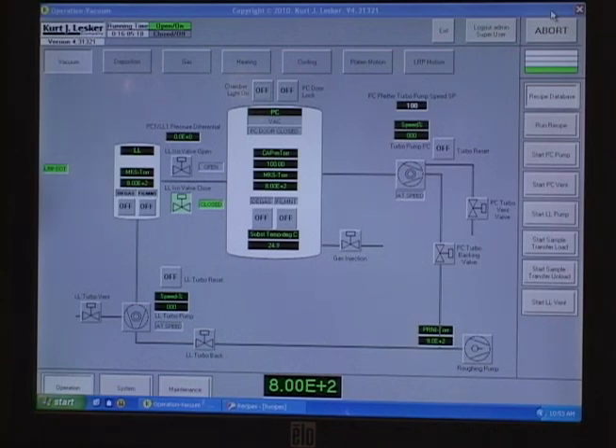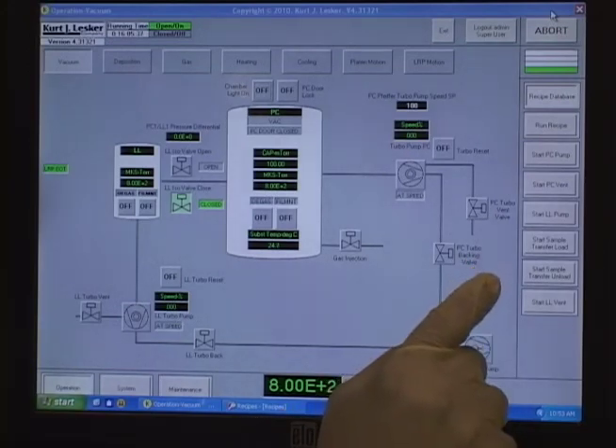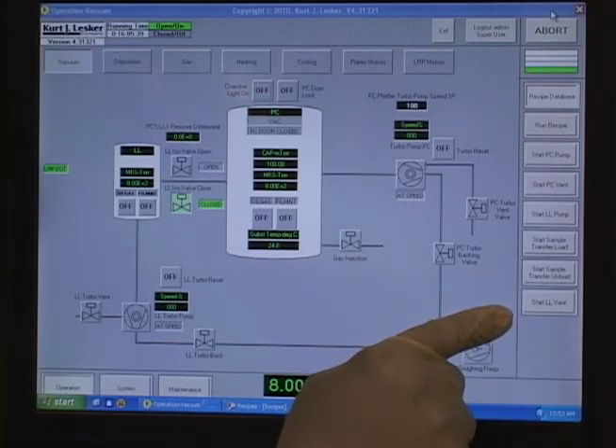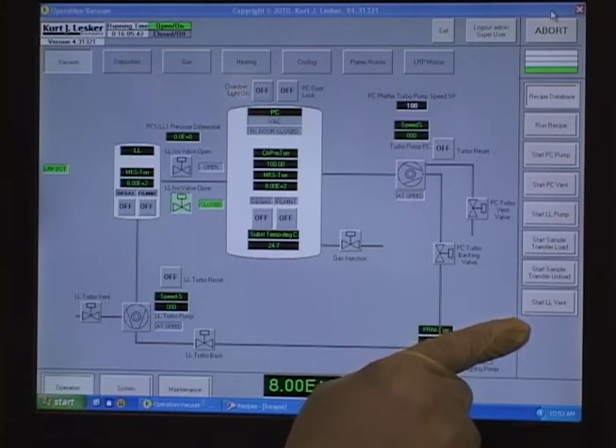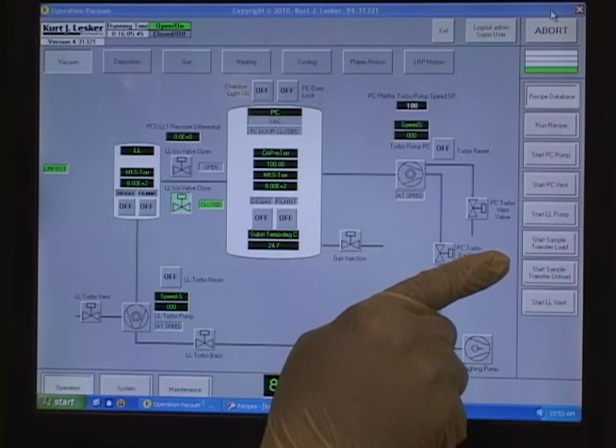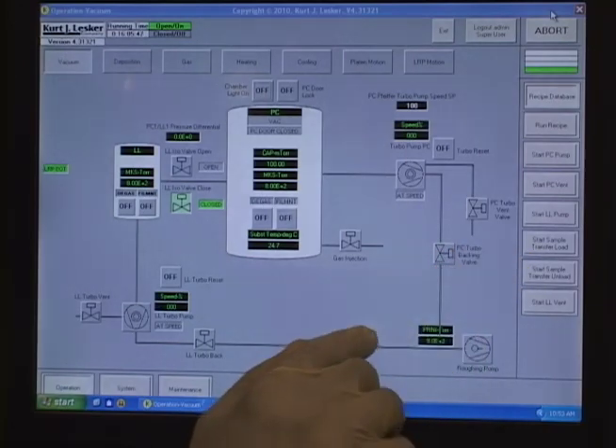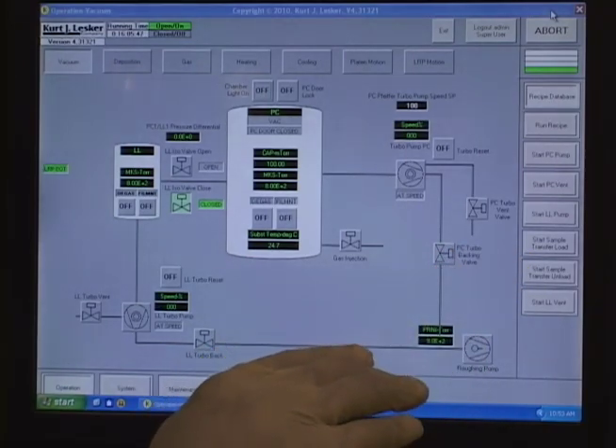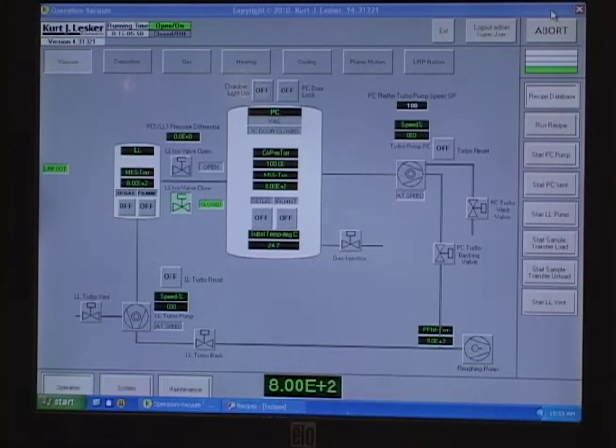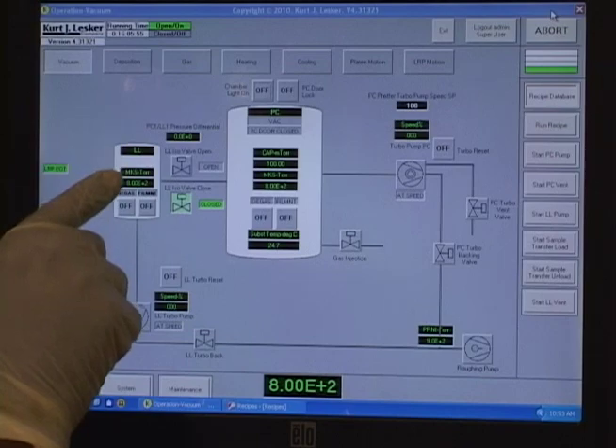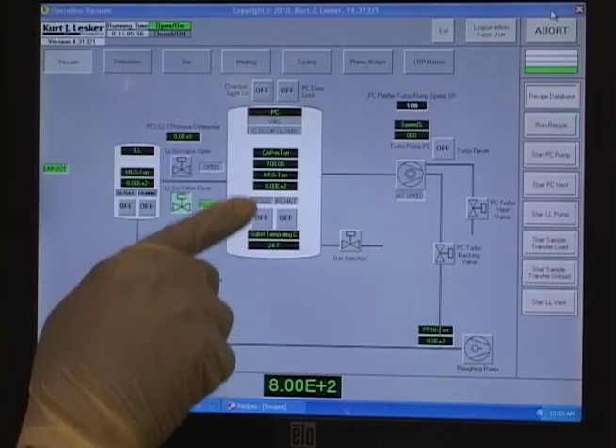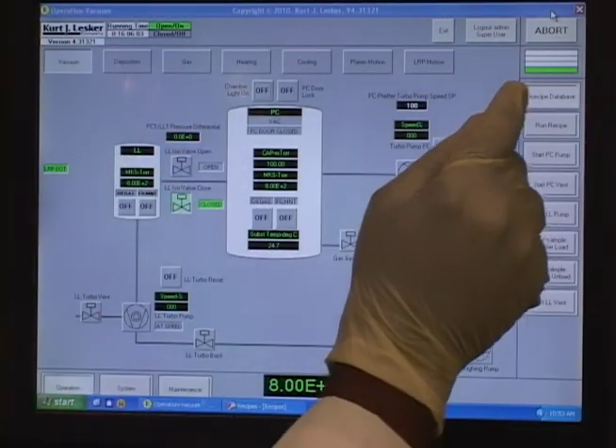Then the next step is to transfer that sample into the deposition chamber. And we do that by the third button from the bottom, which says Start Sample Transfer Load. So there's a mechanical arm that would actually transport our sample from the load lock to the deposition chamber. That's actually done by a recipe.